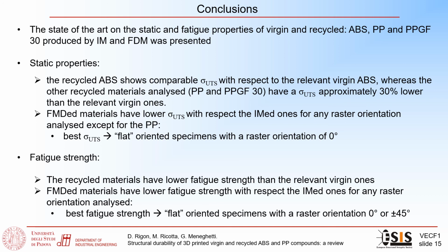Regarding the fatigue strength, the recycled materials show lower fatigue strength than the relevant virgin ones. FDM materials show lower fatigue strength with respect to the injection molded ones, over which the best fatigue strength was obtained on flat-oriented specimens with a raster orientation of 0 degrees and plus minus 45 degrees.